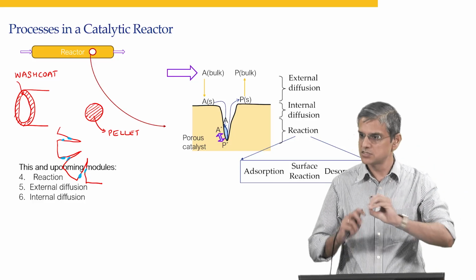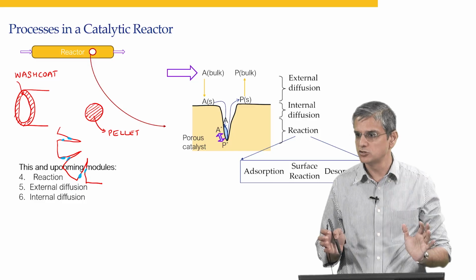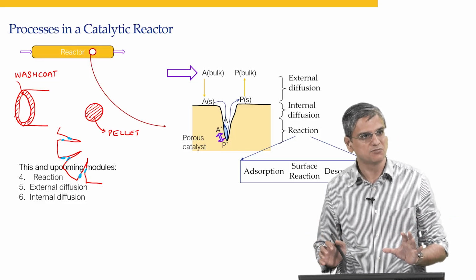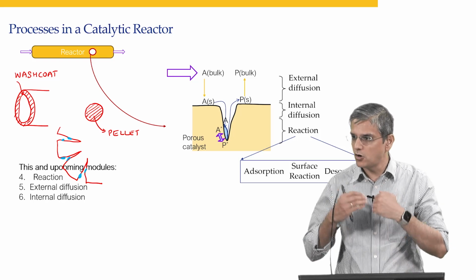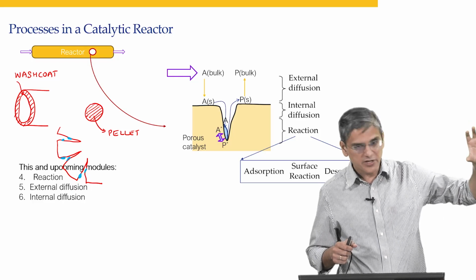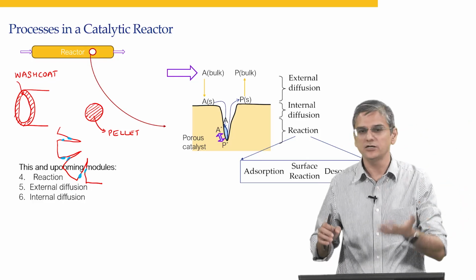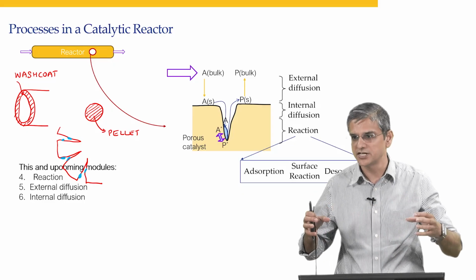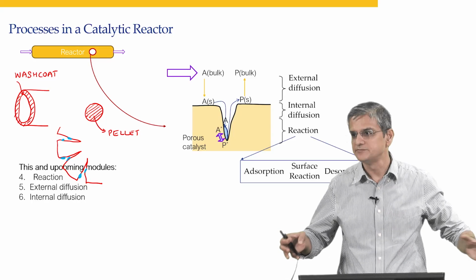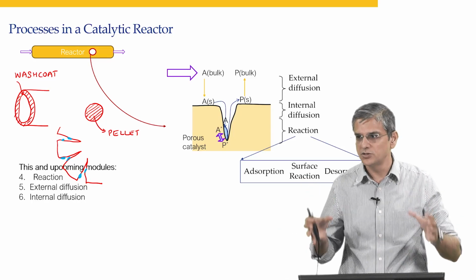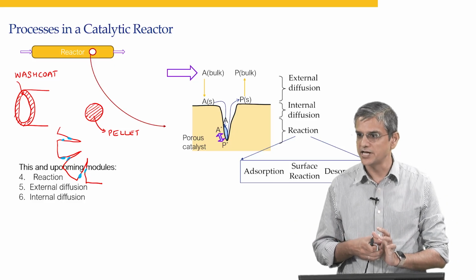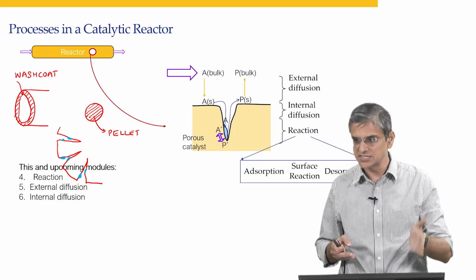So, you take that catalyst, you put in water so that it goes into the pores. Because the catalyst is porous, you keep it soaked for some amount of time. After some amount of time, all the water would have gone inside the pores. So, think of it like a sponge. Okay. So, how much water are you putting? You are putting just the right amount of water that the sponge gets soaked, not so much water that the sponge starts overflowing. Okay. Then what you do is you dry it, maybe overnight or maybe for 24 hours. Water goes away, the salts stay.